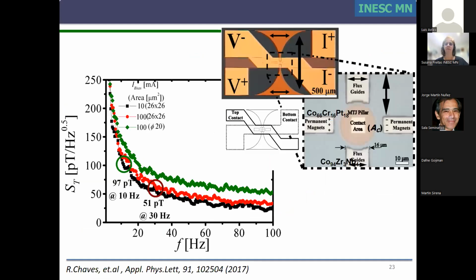Another strategy was to increase the area. So let's increase the area. And this is an example. I'm sorry for the density of this slide. Let's look at the geometry. We have one sensor, which should be of micrometric dimension. Let's increase the area to 26 times 26 micrometers, diameter 20. 26 micrometers is a large sensor, and we see that the signal improves with the area. This example shows that we can detect around 50 to 100 picotesla at low frequencies with these sensors. But let me remark again that 26 micrometers is a large device.